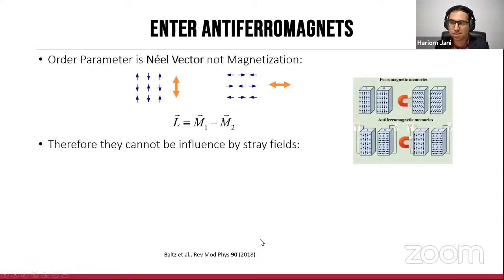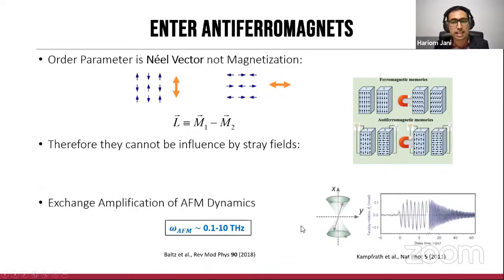But the crucial feature that they hold is that because of their effectively cancelled out sublattices, from far away they effectively behave like non-magnetic objects. They are not influenced by stray fields, although they actually have very robust internal order. They exhibit ultra-fast dynamics, which has really brought the attention of the spintronics community to these materials, which for a long time were not given significant attention because they were very difficult to study and manipulate.